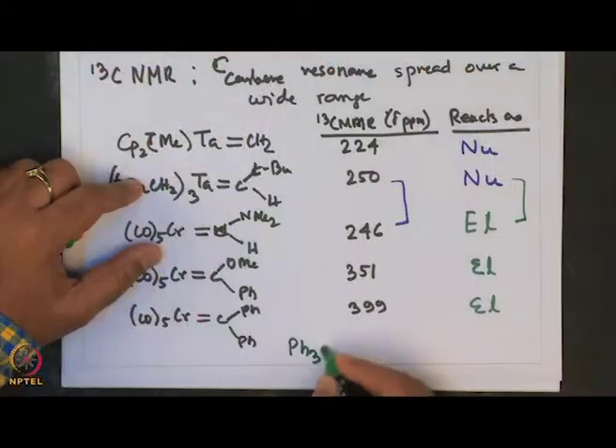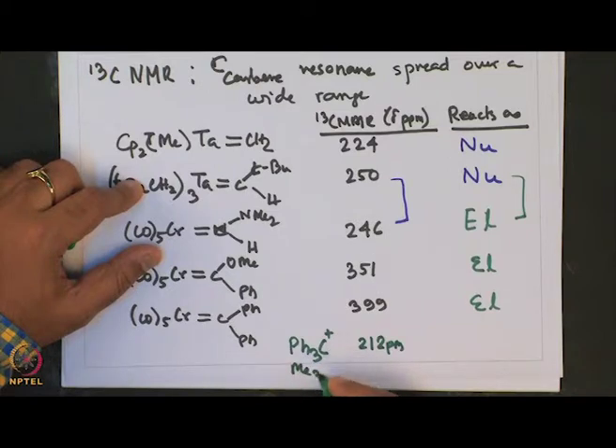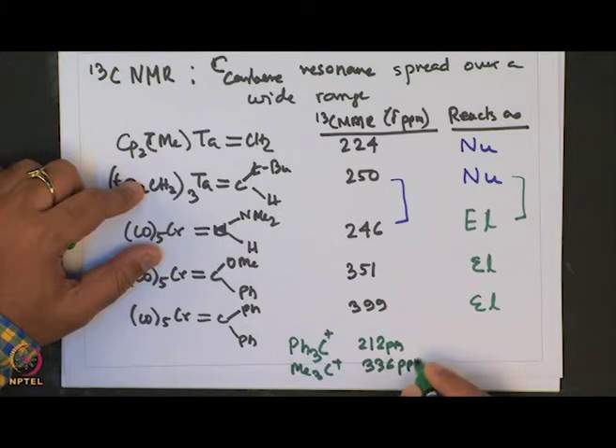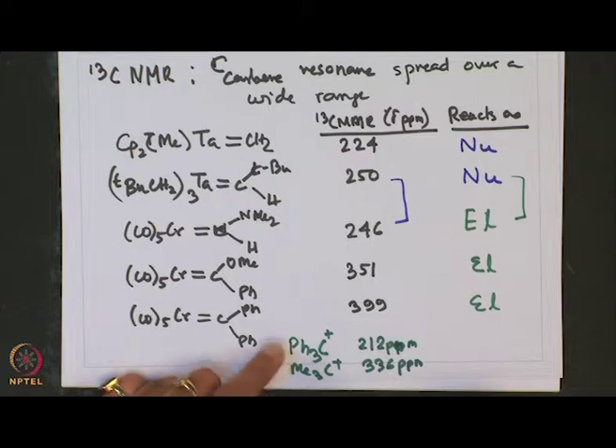For example, for the trityl cation, Ph3C plus, the delta is 212 ppm, and for the methyl-substituted cation, Me3C plus, this is 336 ppm. So, even for this cation, on going from methyl to phenyl substituents, there is a huge difference in chemical shift. So, from the carbon characterization, one can say that even though the carbene moiety has been characterized, any attempt to draw correlation between their chemical shifts and the reactivity of these complexes may not be useful, because there may be carbene complexes which have comparable chemical shift but an equally opposite kind of reactivity, as can be seen from this Schrock and Fischer carbene complexes which behave totally different from each other.